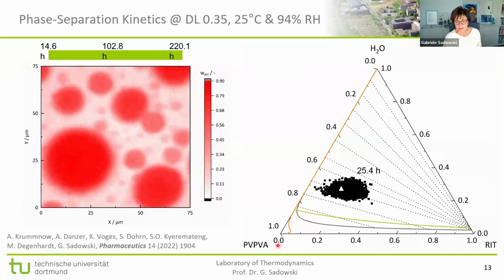This is the polymer, PVPVA. This is ritonavir. The dry system would be on this axis. And what we see, that's the solubility line of ritonavir in PVPVA, which is quite small. But ritonavir, you have seen, is a big molecule, so usually it doesn't crystallize even if it's supersaturated. So that's not a problem in this case. But what we see is a huge miscibility gap. So ritonavir and water have a huge immiscibility. And even if we add PVPVA, this doesn't change a lot. So that means we have a huge miscibility gap, and that means that these samples here will demix.